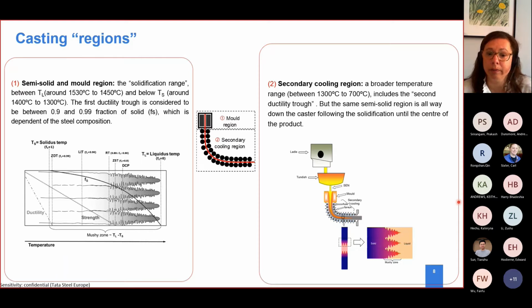The second region is the secondary cooling region. This one has a much broader temperature range, more or less between the 1300 at which it exits the first region, down to about 700. Below that, it's not normal. It could happen, but it's not normal in continuous casting because the steel becomes too stiff and too cold to be able to move it and further process it, or at least to extract it from the machine.